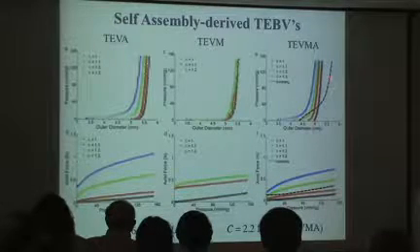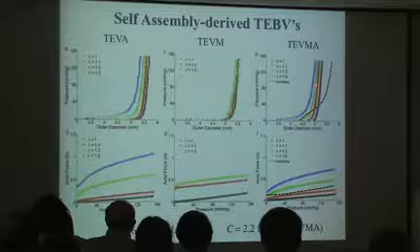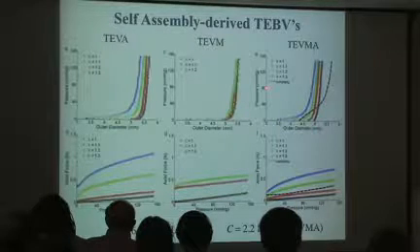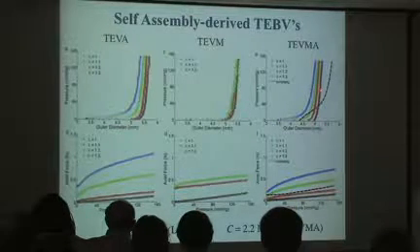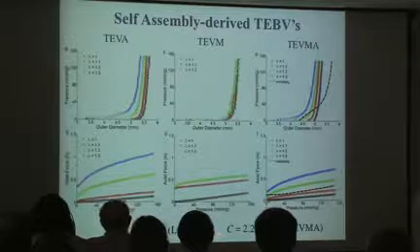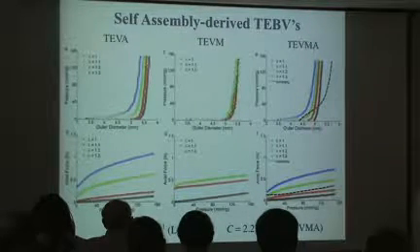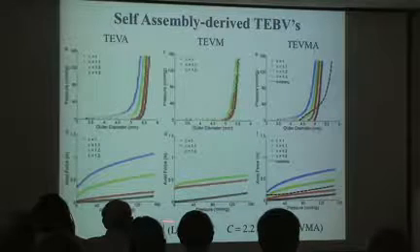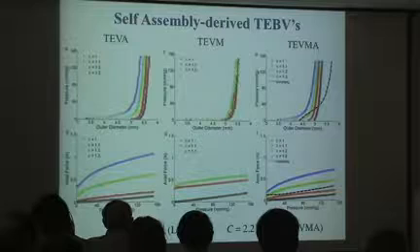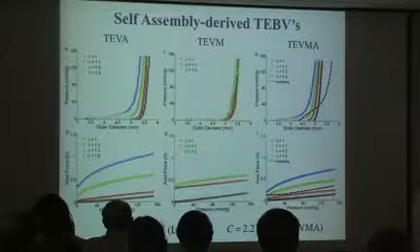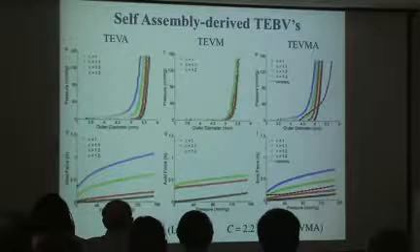If we look at the compliance over the physiologic range, let's say 120/80 or maybe a little bit higher, the compliance of these vessels is about 2.2 inverse megapascals. A little bit lower than this representative coronary artery, but actually within the range that's reported for human vessels, right? So these vessels look pretty good.